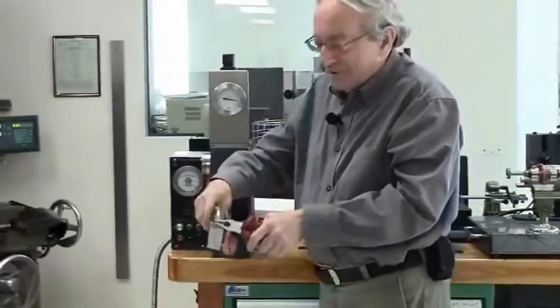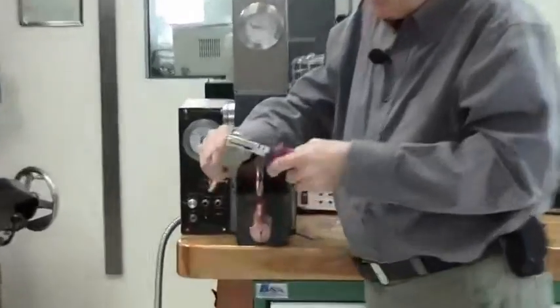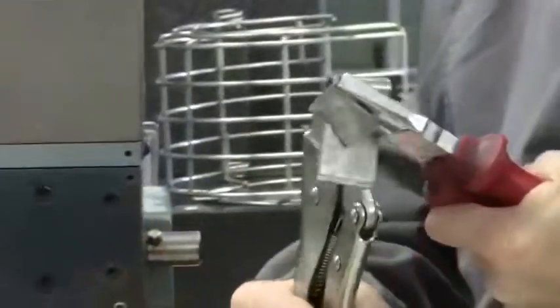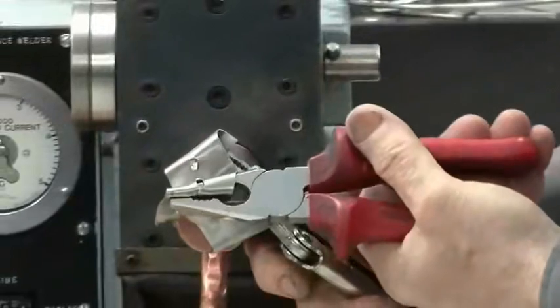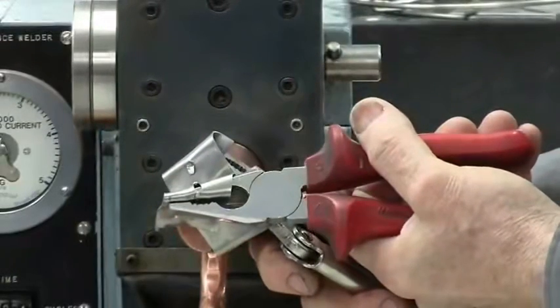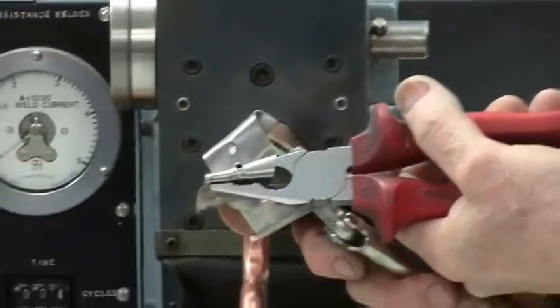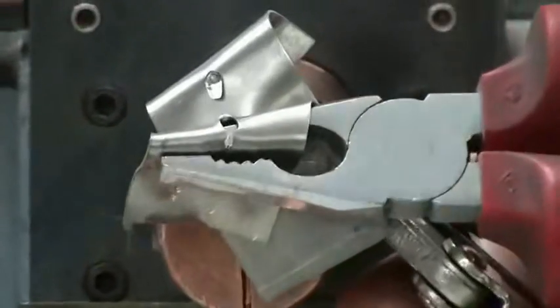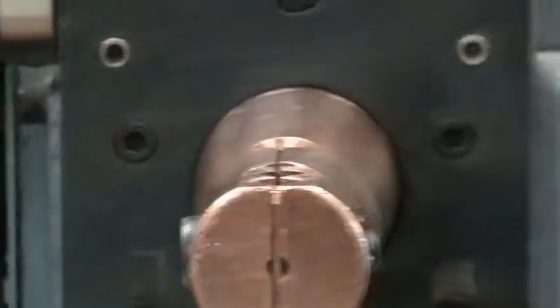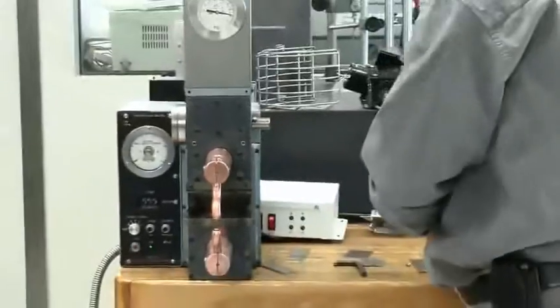So now let's zoom in and we start doing the tear test. So the first weld, the 2 cycles, should be open. Even the first weld was good enough, actually. You can see what happened. Look at it. The metal tore out from the hole without opening the weld. So obviously 2 is the right number. One is too weak, for sure, but 2 is the right number.